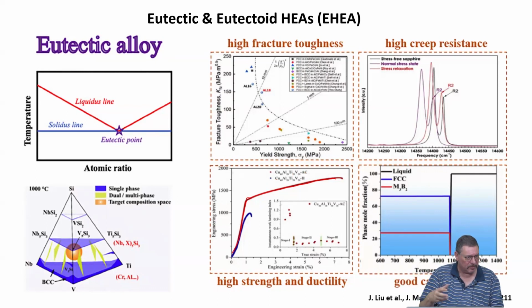So you can make materials which have lower density, but still having the same or similar mechanical performance. And high entropy systems always have this tendency that they can be used up to a little bit higher temperatures, because the microstructure stability tends to be larger. So it means it could be, but this is active research. People are not, and I also am not quite sure that this is true in all cases in general. So you could design materials which have lower density but higher working temperature.